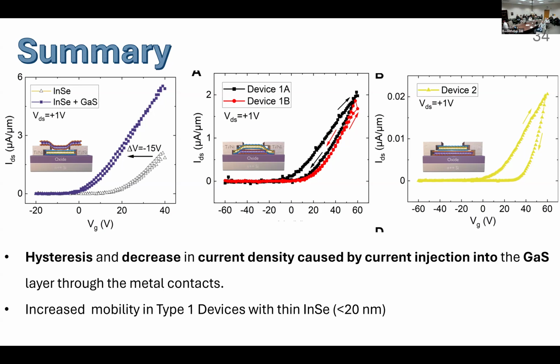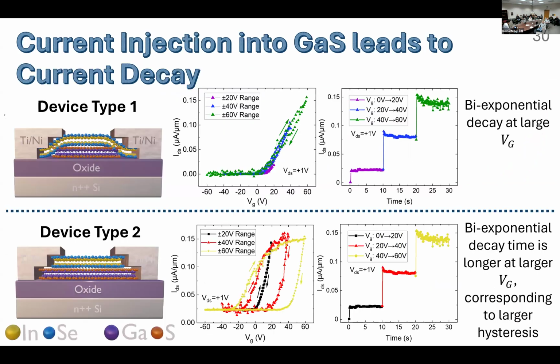Well, you go to slide 30. Yes, 30. And so you talked a little bit about the time dependent measurements and how you get your different curves. Could you elaborate a little bit more on how that affects the hysteresis? Yes, so the decay in the current is telling us there's current going somewhere else. So current going into the gallium sulfide is what we believe is causing this hysteresis. Ideally, the gallium sulfide would be an insulating material that no current could flow through it. But because of the presence of traps, whether defects introduced during the growth process, or, since this device is very air sensitive, oxidation from the oxygen in the air or the humidity, these can all introduce traps into the gallium sulfide layer.